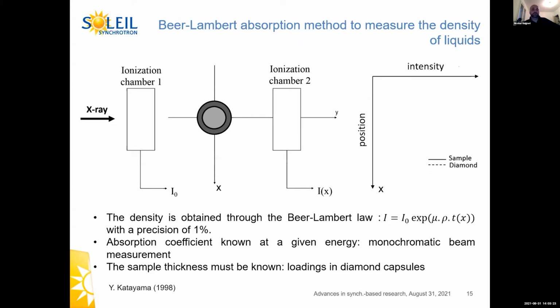The last technique I would like to show you today is the Beer-Lambert absorption method to measure the density of liquids. This method is not new. Actually, it's available in many synchrotrons. It's very straightforward. What you need to do is just scan the sample in front of a monochromatic beam to get the absorption profile. And then you use the Beer-Lambert law to get the density of the liquid. With the Beer-Lambert law, you have the density, the absorption coefficient, and the thickness of the sample. So the density is what we measure. The absorption coefficient is known at a given energy. This is why we use a monochromatic beam. And the thickness is fixed because loadings are done in diamond capsules.